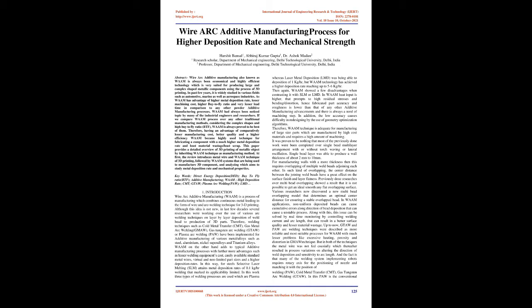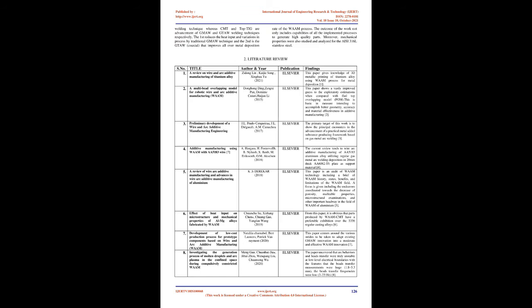Then again, WAAM showed a few disadvantages when contrasted with SLM or LMD. In WAAM, heat input is higher, which leads to high residual stresses and bending or distortion. Hence fabricated part accuracy and roughness is lower than that of any other additive manufacturing advancements, and there is always a need for a machining step. In addition, the low accuracy causes difficulty in redesigning by the use of geometry optimization algorithms. Therefore, the WAAM technique is adequate for manufacturing large size parts which are made of high cost materials and require a high amount of machining.